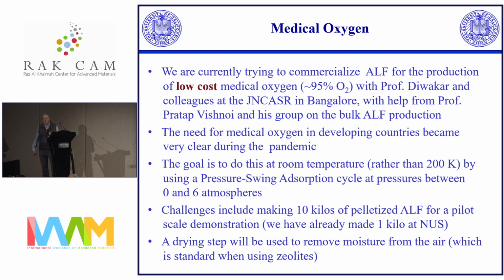And so Diwakar's idea, which I thought was great, and I've not been so ambitious, he said, we don't really want to cool it, but what we can do is just use higher pressures. Because even at room temperature, if we use higher pressures, we're going to get quite good capacities. So our aim is to use a pressure swing adsorption cycle at pressures between kind of 0 and 6 atmospheres. It's not very high. And I'm hoping, by the end of this first quarter, we'll know if we can do that.